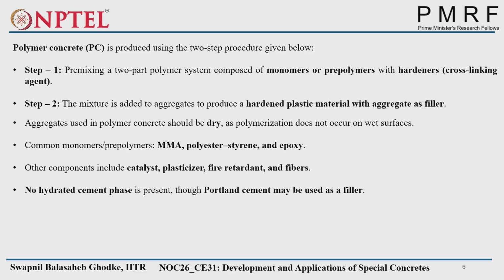So one more important point we have to consider here, that is aggregate used in polymer concrete should be dry, as polymerization does not occur on the wet surface because it requires the heat to initiate the processes. So on the wet surfaces, it will not start the process of the polymerization. And the common monomers: MMA, polyester-styrene, and epoxy. Other components apart from the monomer that we require: catalyst, plasticizer, fire retardant, and fibers.